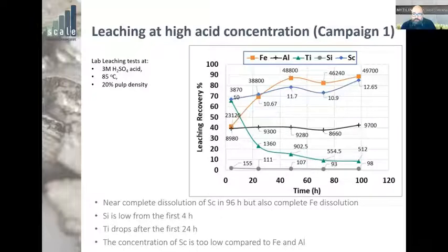You can see that if we spend 96 hours of leaching, we can get almost 85% of the scandium out, which still is just 12 parts per million in terms of pregnant leach solution. So the data labels indicate the concentration in parts per million, while at the same 96 hours we will get close to 50 grams per liter of iron, so complete dissolution of iron as well.